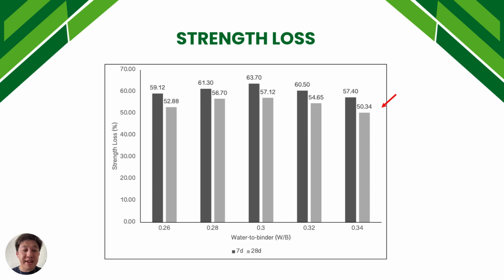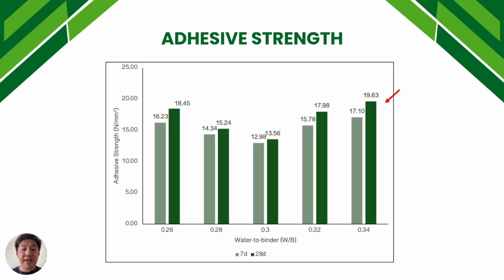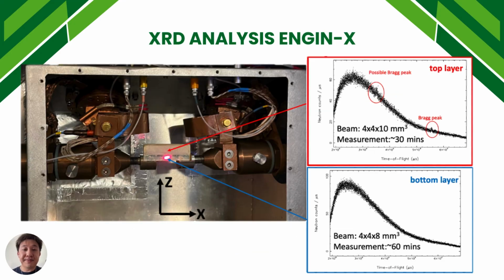We also carried out the strength loss testing, and found that the 0.3 water to binder ratio has the highest strength loss. For the adhesion strength, we also found that the 0.34 water to binder ratio has the highest adhesive strength, which is 17.10 megapascal for 7 days and 19.63 megapascal for 28 days.